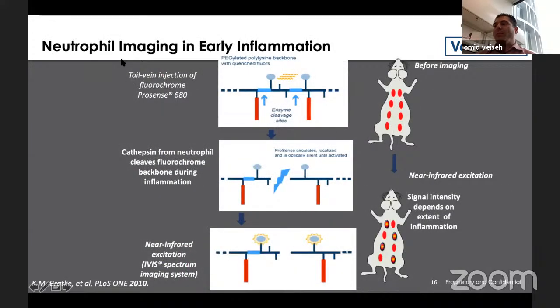I mentioned that we had this subcutaneous assay where we would implant materials in discrete positions, and these are 300 micron spheres. So once you inject them into these positions, they don't really go anywhere. They stay exactly where you injected them. And we wanted to evaluate how the immune system of the mouse was reacting to these materials. So we developed this ProSense imaging approach, whereby you can inject a dye, which is normally quenched, but in the presence of cathepsins, and cathepsins are secreted enzymes by macrophages and neutrophils. So wherever you have activated macrophages and neutrophils, you would get a fluorescent signal that would evolve. And that would allow us to quantify exactly how much response the immune system is orchestrating against a given material.